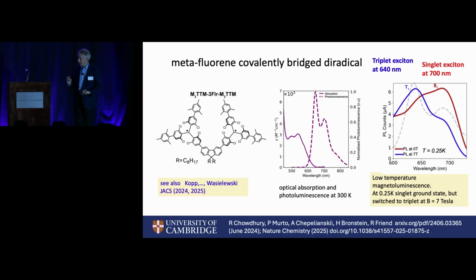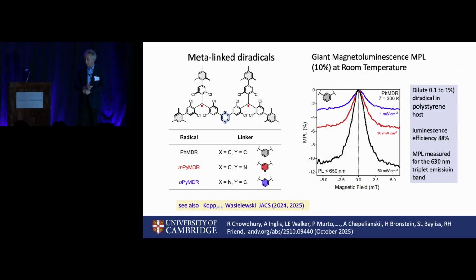Should have said that. So that paper was all about low temperatures. We've now got things happening at room temperature. And the huge surprise is that there's a massive change in luminescence with very weak applied magnetic fields. The right-hand panel shows that within 2 millitesla, which is tens of times more than the Earth's magnetic field, but not much, we can get up to a 10% modulation of the luminescence.